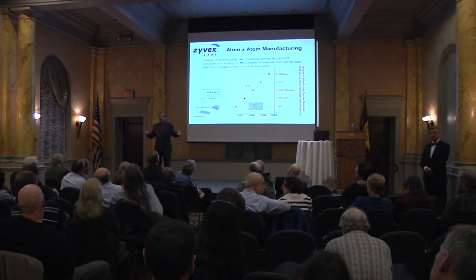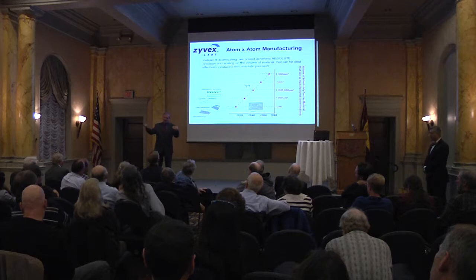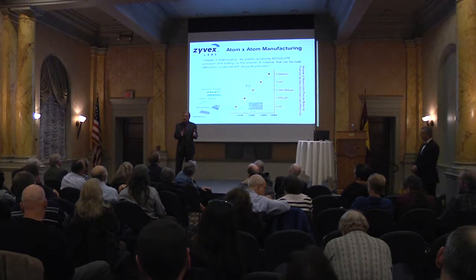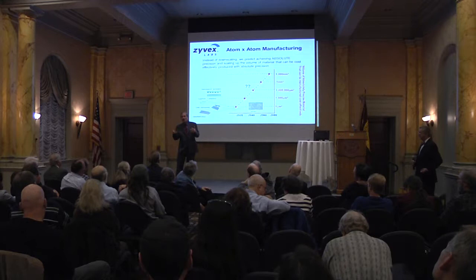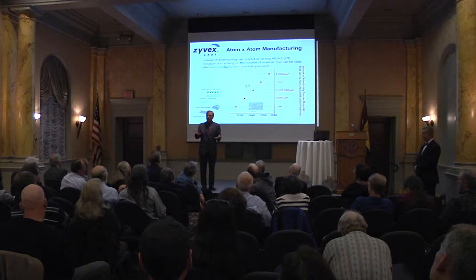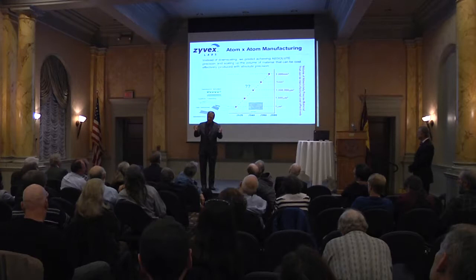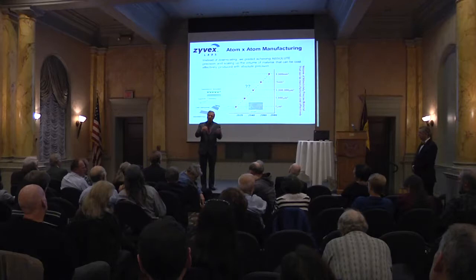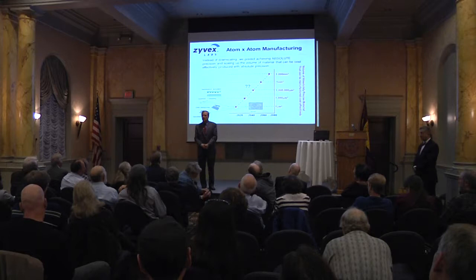I'm relying on the self-assembly of the silicon, the disilane coming in to arrange itself into the silicon crystal. But I'm controlling where that happens, okay? So I think of it much more as a top-down approach. You could argue it either way. I trust self-assembly to do simple things, and epitaxy is a simple thing that self-assembly can do very well. I don't so much trust self-assembly to do more complex things. With most bottom-up self-assembly approaches, you're always driving towards a minimum energy configuration. And often what you'd like to have is not in a minimum energy configuration. Effectively, what we're doing you could conceive of as templated self-assembly, and so it's a combination of bottom-up and top-down. I think of it much more as top-down, but I think it's sort of semantics to some extent.